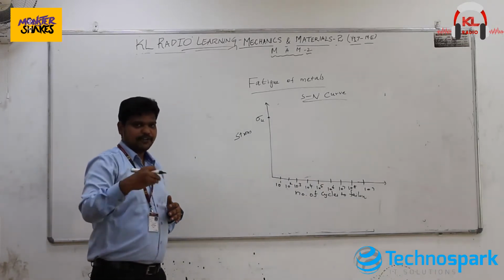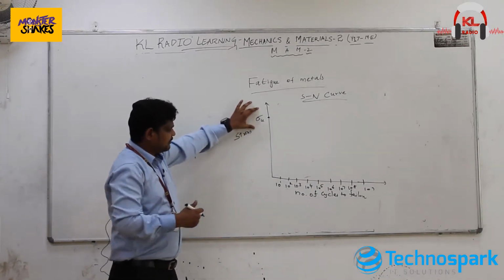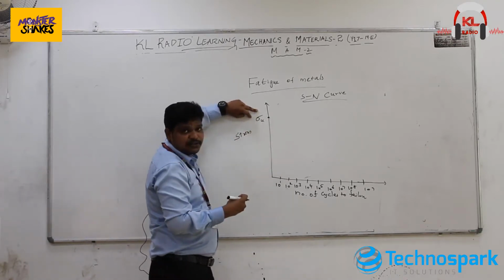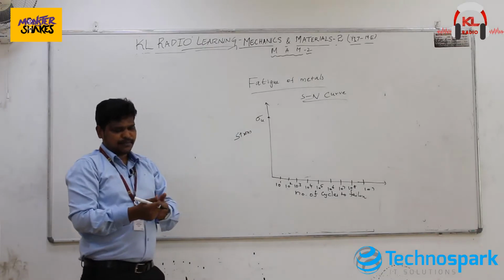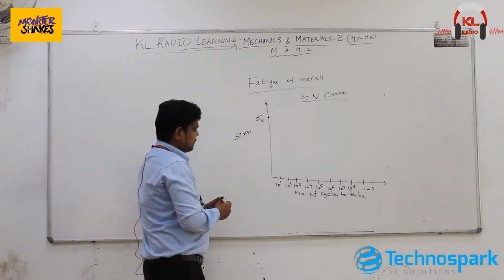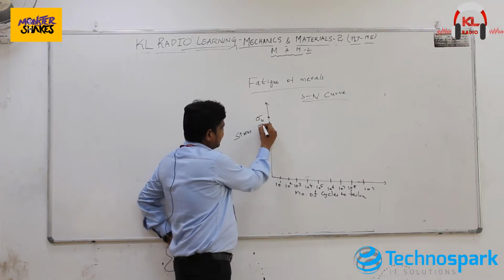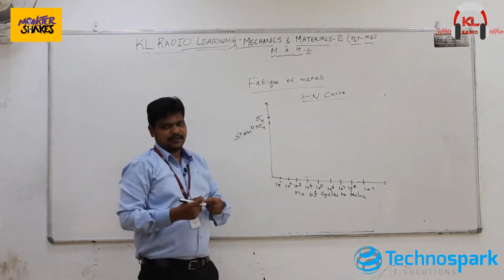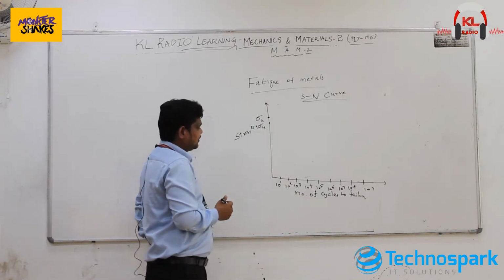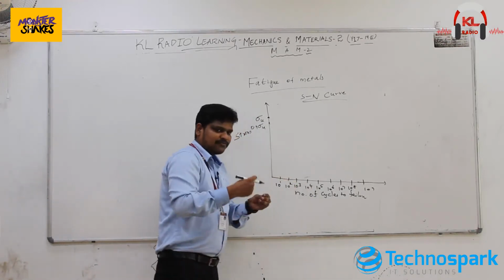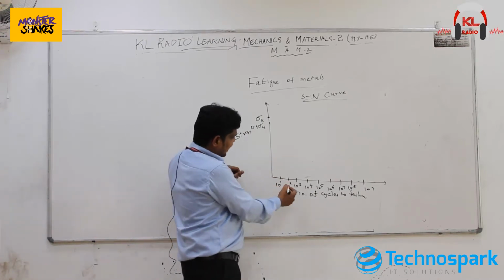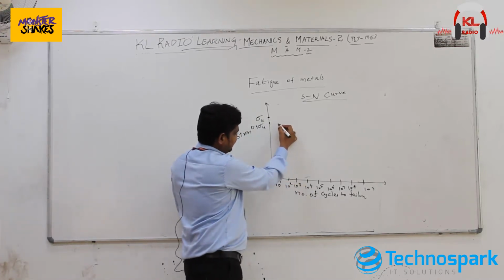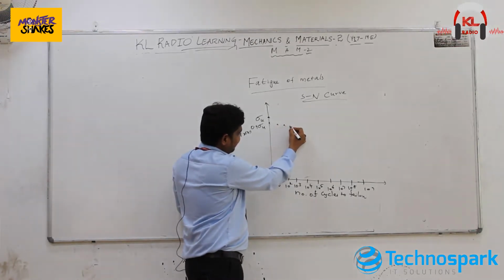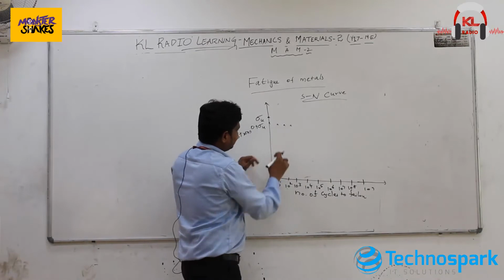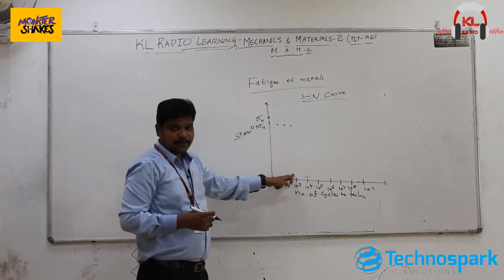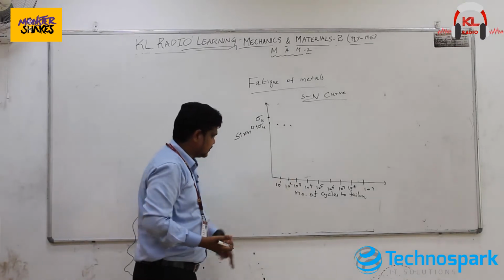So as you know, when you just apply a tensile load and the stress is equal to the ultimate strength, obviously that metal will fracture, right? So when I choose 0.9 of the ultimate strength as the initial stress level, and increase the number of cycles by rotating a beam, we notice that up to 10 power 3 cycles, 1000 cycles, there is not much difference in the failure. It happens at almost the same stress level until 10 power 3 cycles. It is a low cycle fatigue test.